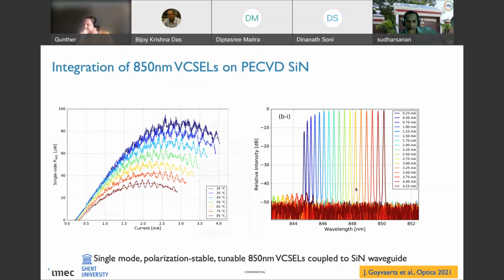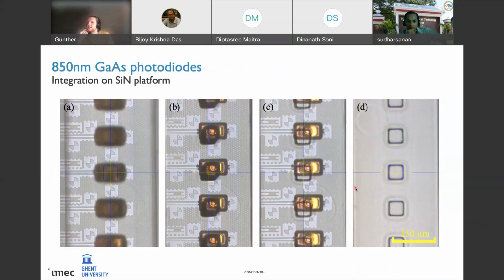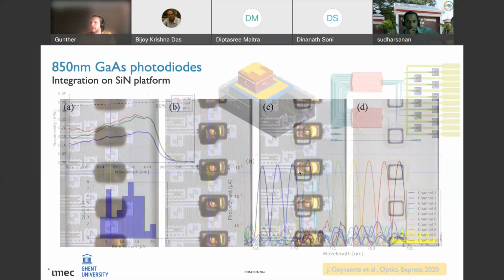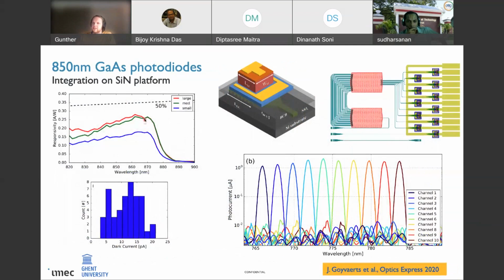So similarly, we also printed gallium arsenide photodiodes for 850 nanometer operation. In this case, it shows the array printing of these photodiodes. Here we don't have the best quantum efficiency at the moment. It's less than 50%. But here the idea was mostly to demonstrate the concept, microtransfer printing short near-infrared photodiodes on silicon nitride waveguide circuits.